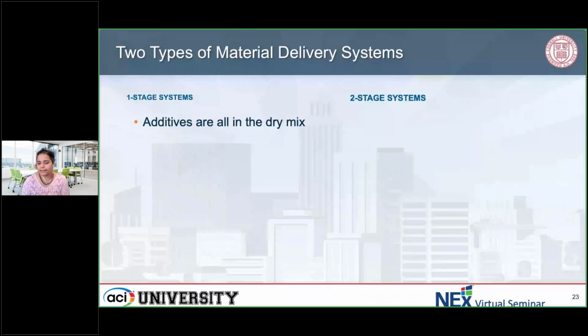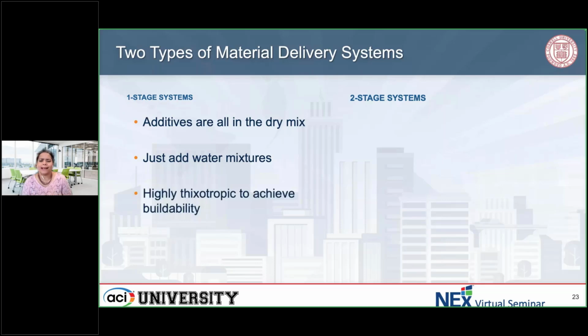In the one-stage system, it's almost like the bag mixes you get for UHPC, ultra high performance concrete, where you have all the additives, everything that goes in the bag. You have your mixtures, you could have like fibers, polymeric fibers, and then you can just add water. So you have a pumping system where the dry material comes in and the water gets injected, and then you mix the two. And right after you mix them, these materials are highly thixotropic.